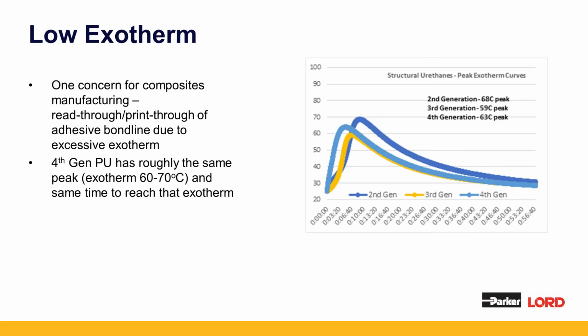With the new 4th generation structural urethane, you can actually get down to as little as 90 seconds. One of the concerns with using fast curing urethane is they typically generate quite a bit of heat, or exotherm, during the curing process. So acrylic adhesives, or MMAs, some of the earlier generations certainly are notorious for generating so much heat that when used on composites such as FRP or thermoplastics, they can actually begin to melt and deform the finished part, leading to visible bond lines through the part.